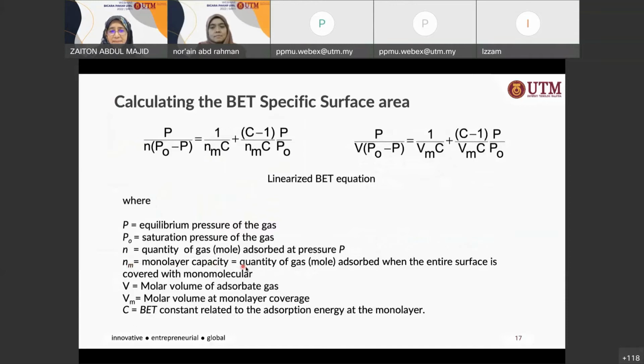Nm, which is the monolayer capacity, the quantity of gas in terms of moles adsorbed when the entire surface is covered with a monomolecular layer. Or you might want to use the formula in the form of volume. The C here is a BET constant, which is related to adsorption energy at the monolayer. V is the molar volume of the adsorbate gas at the specified equilibrium pressure, and Vm is the molar volume at the monolayer coverage. This is the linearized BET equation that we use. Some people prefer the one with number of moles, some prefer the one with volume. You can use either one.